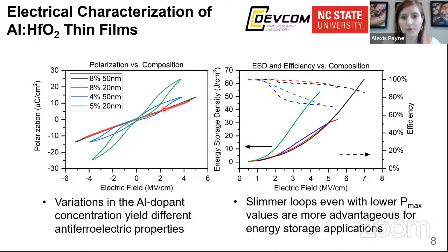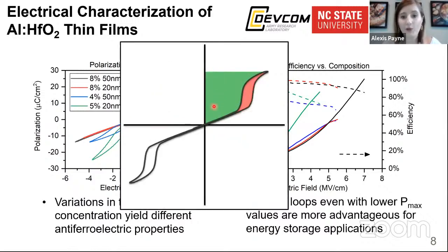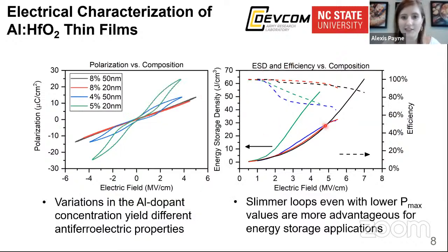When thinking of this from the energy storage density viewpoint, you have to remember this plot I showed you at the beginning, where the green is the energy stored and the red is the energy lost. So you can see in our calculations here of the ESD and efficiency at increasing fields that for the 4 and 5%, the dashed lines, the efficiency drastically decreases with increasing electric field. And that can be seen with the wider loops. We get down to efficiencies of 60%, as compared to the 8%, which maintains its efficiency all the way through high electric fields, above 80%.